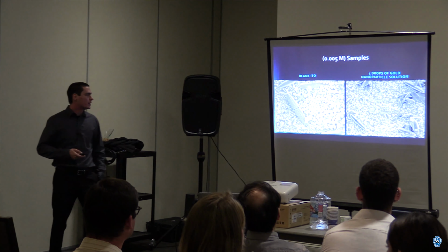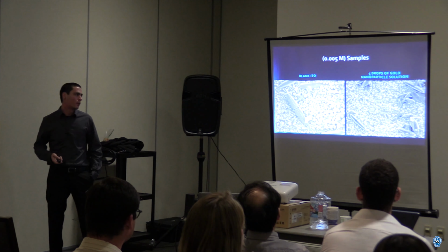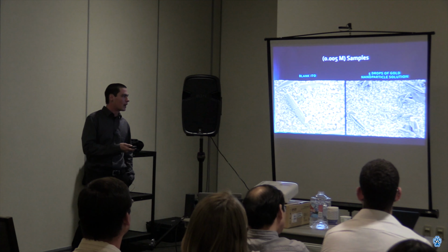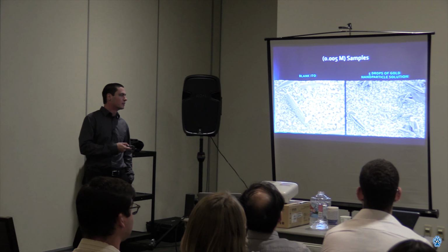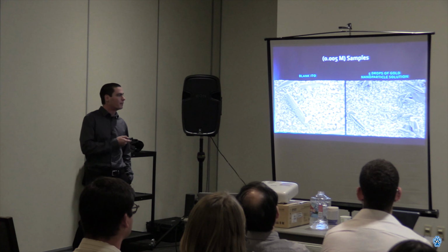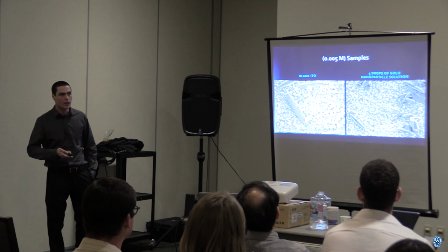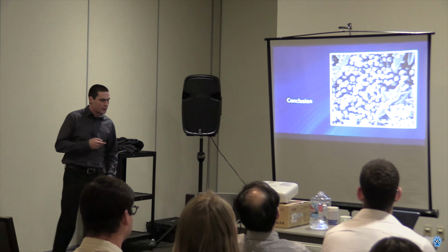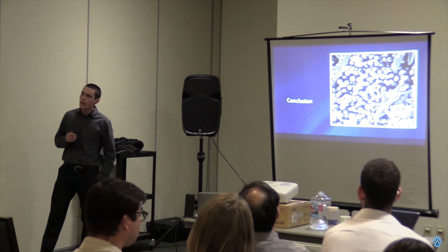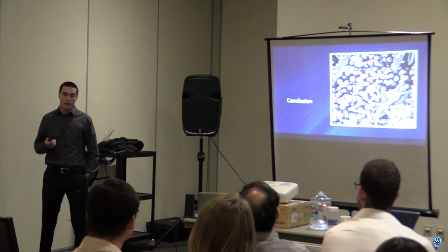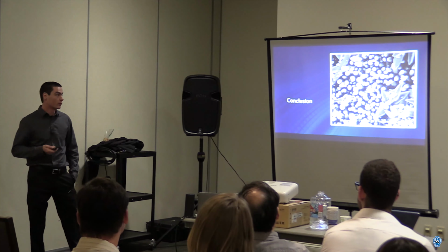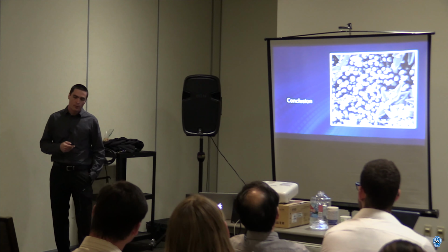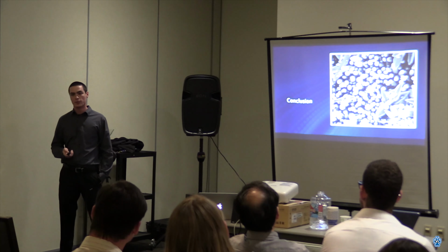And then with the third sample of 0.005 molarity, there didn't seem to be much change, as you can tell. I mean, yeah, there's a little bit less of these larger structures, but maybe that's just the location on the surface that I was looking at. And so my conclusion is that the 0.01 molarity sample after 5 drops of gold nanoparticles gave us the best image or surface, but the current readings from the 0.05 molarity sample was the most uniform.